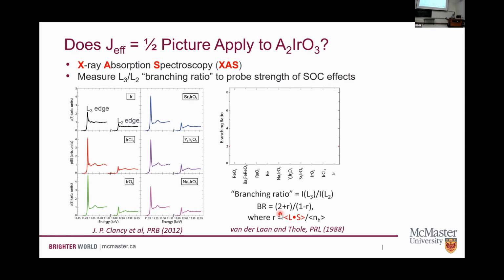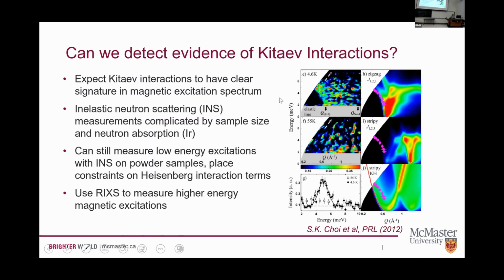Okay, so in the case where we have negligible spin orbit coupling, this branching ratio, so the ratio of this intensity to this one, should give us about 2. If we have this J effective 1/2 state, we expect to see a much bigger peak at the L3 edge and a little peak at the L2 edge. And so we should see a big branching ratio. And so if we look at some of these rhenium-based compounds, we see something that looks pretty statistical. We move into these iridates, honeycomb iridates, layered perovskite iridates, different versions here. We get these big branching ratios that, again, are indicating to us that we have maybe interesting physics from this strong spin orbit coupling.